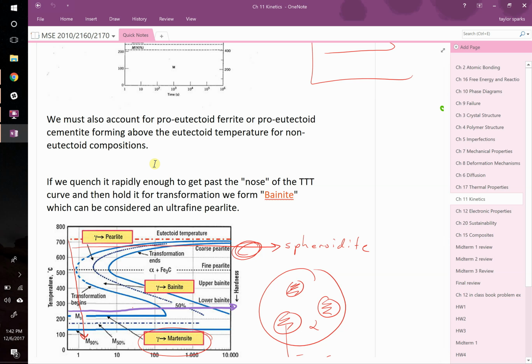But in practice, it depends on how far you are below that and how long you hold it there, what sort of microstructures you actually achieve. If you do it in this region, above the nose, this whole thing is called pearlite. The bottom end would be fine, the top end would be coarse. Out here should be spheroidite. It's not drawn there, right? And then if you do it below the nose, you form bainite. The only difference between bainite and pearlite is the thickness of these lamellae that form.